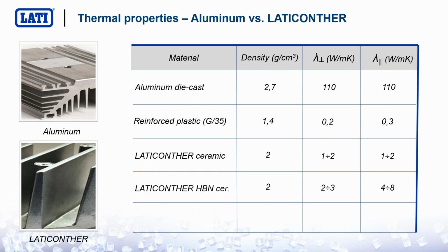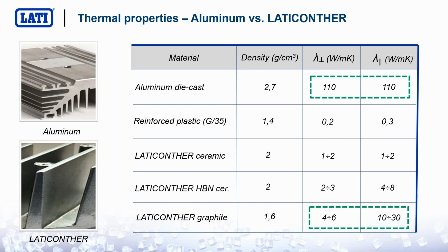But let's give a look at what happens when we use graphite-based materials, for those applications where the electrical conductivity of the material is not a problem. What is the performance of these materials? A typical graphite-based thermally conductive compound has a density between 1.5 and 1.6, so we are close to half the density of aluminum. And the thermal conductivity is, as we have seen before, from 4-6 watt/meter Kelvin through plane up to 30 watt/meter Kelvin in plane. You may say that these numbers are still very low when compared to aluminum, but we will see that in many applications, the higher thermal conductivity of aluminum can be redundant. So we will focus on these two materials here, aluminum die cast and graphite-based thermally conductive plastic compound.